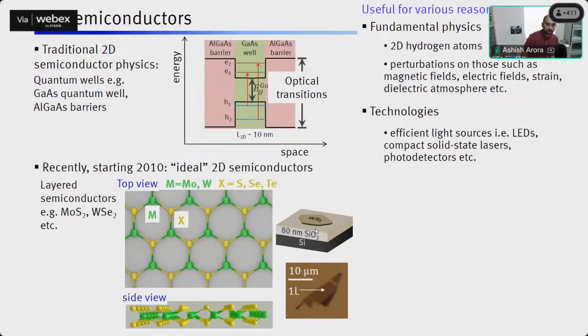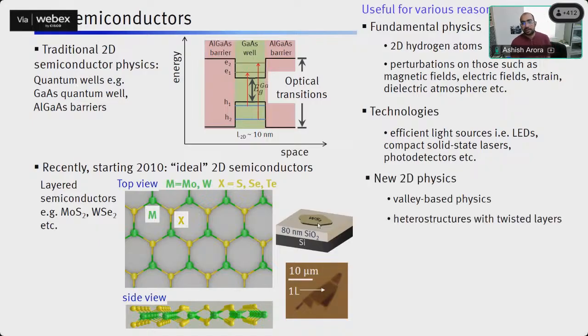Now, such a thin film, meaning this tungsten disulfide, is 100,000 times thinner than your hair thickness. It's very thin, just one atom thick. How do you see it? Well, to see it, we place it on this special substrate, and there are interferences which take place between the silicon dioxide and this film, which make the absorption in the film grow larger, and this absorption makes us see the film better. So even a single layer film is visible.